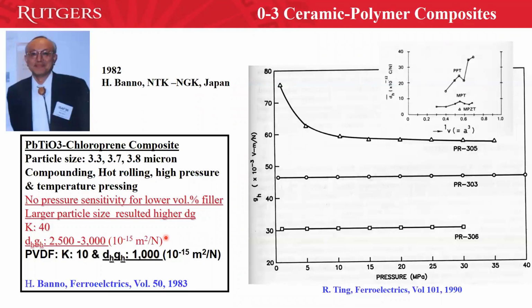So in 1982, H. Banno put a bombshell in the community. He introduced several different types of composites. And these composites are 0-3 composites made by lead titanate particles. We believe that he made them by chemical processing with controlled particle size, and sometimes in the composite he mixed different particle sizes. Finally, he announced a composite with d_h g_h ranging between 2,500 to even 3,000 or more. And that was really a breakthrough, compared with the old 0-3 composite of PZT polymer, or even compared with the PVDF properties.